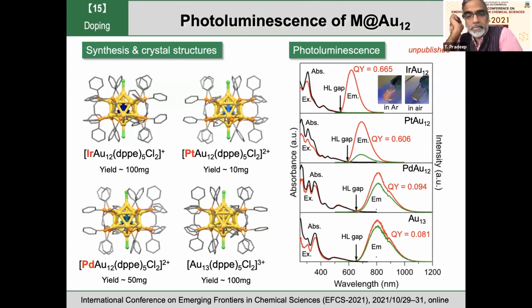Yeah, because these several methods, they may have different radii, right, for the dopants? Platinum and iridium, they are very different. So how can this different size of the metal atom go inside your Au13, right? Yeah, actually, when the size is reduced, the packing of the gold becomes more comfortable. We see the change in the length after doping a smaller dopant. So maybe that will also rigidify the core to suppress the non-radiative process. So will that at least contribute to the different luminescence properties of your cluster? Like the emission wavelengths are quite different, right?